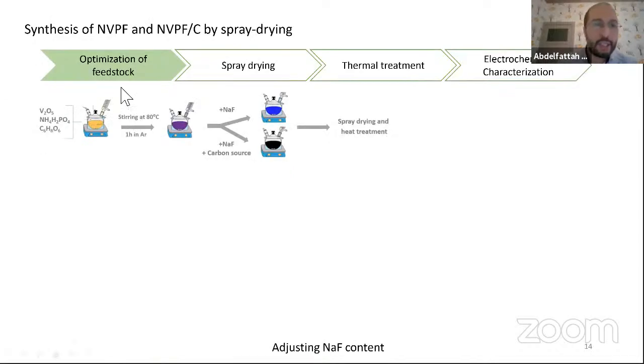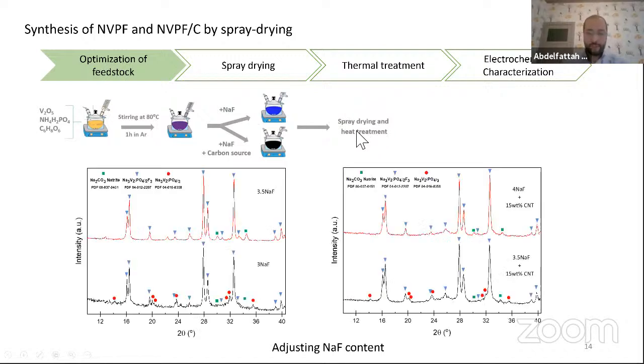So in the case of NVPF material, we mix the precursors based on vanadium and phosphorus, and we also add some carbon sources. Then, when we mix them, we have two options. Either we prepare the pure material without the addition of carbon sources, or we add the carbon sources in order to prepare the composite material, and then we do the spray drying and the heat treatment.